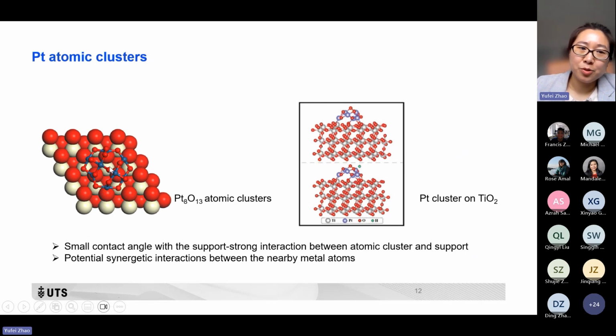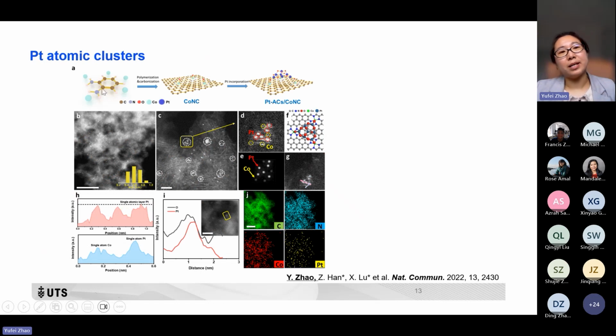In this kind of atomic structure, we can see it possesses the advantage of quite a small contact angle with the support. That means it's different from nanoparticles with very obvious 3D structures. For this kind of atomic cluster, normally it has a quite flat structure to maintain the strong interaction between the atomic cluster and the support. And also it possesses nearby atoms. That means the potential synergistic interactions between the metal atoms may further boost the HER process. So keeping this in mind, we have designed this kind of atomic cluster.